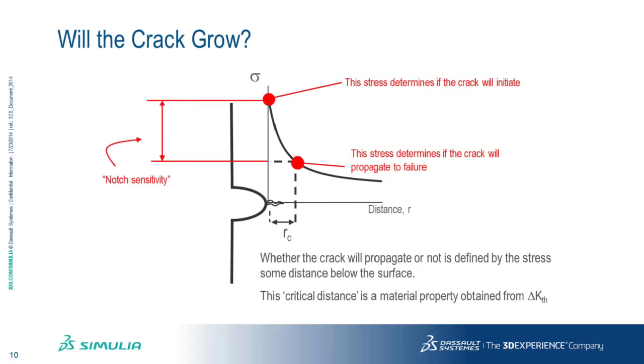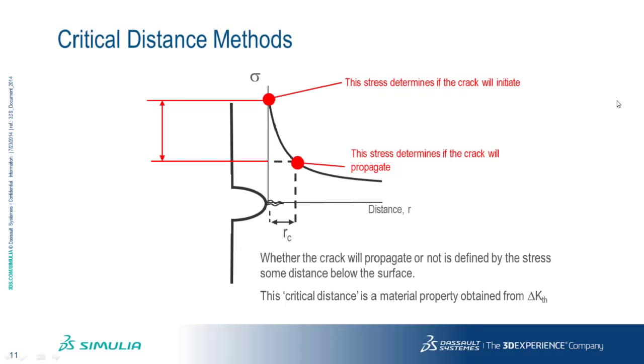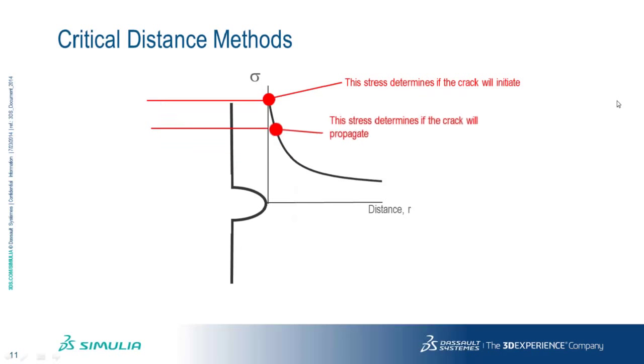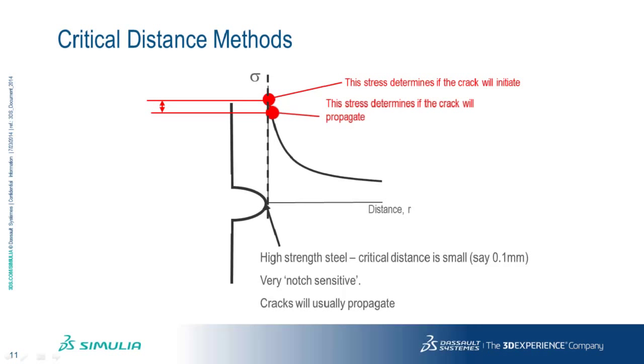We used to call this notch sensitivity in fatigue, but this is a term that we don't really use anymore. So if we have a high strength steel, the critical distance will be very small. It's typically of the order of a tenth of a millimeter. So there may be very little difference between the two stresses, and so if a crack initiates, it will almost certainly propagate. And we used to call these materials very notch sensitive. If a crack initiated, it would almost certainly propagate.